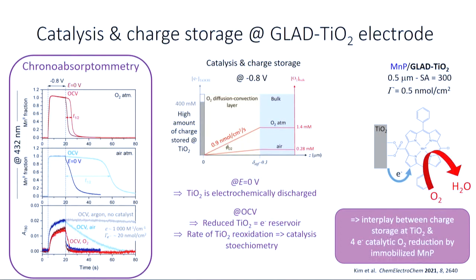So what we did is we applied a very negative potential for a short time, okay, 15 seconds. And at this very low potential, what we assume is that we have a very fast catalytic process because the interfacial electron transfer is extremely fast, so we very rapidly deplete the electrode of the substrate. And we see that we accumulate the manganese 2. Here we focus on manganese 2, either under oxygen or under air. And here we focus on titanium dioxide. So we monitor charge accumulation in titanium dioxide now.